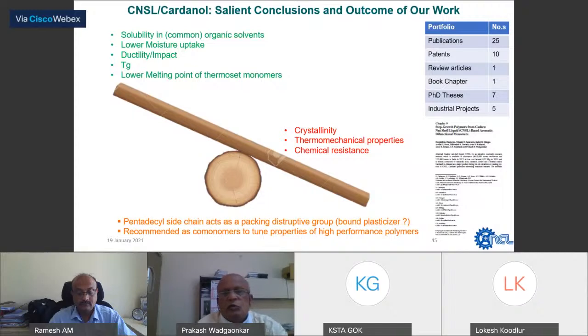And to capture all of that, what we achieved by making these monomers, we have prepared polymers which are soluble in common organic solvents, with low moisture uptake because of the C15 hydrocarbon chain, improvement in ductility, and then modulation of glass transition temperature, of course at the expense of crystallinity, thermomechanical properties, and chemical resistance.